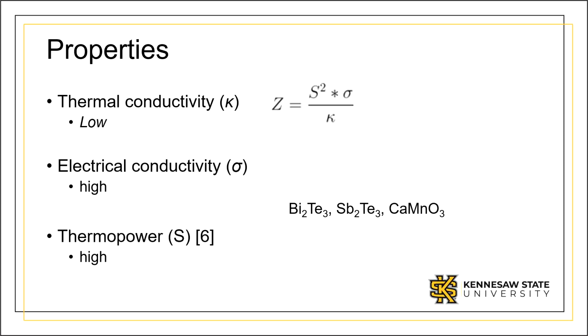There are three fundamentally important properties of a thermoelectric system that must be optimized in order to produce a near-ideal system. Unfortunately, these three properties are closely related and are usually inherent properties of a material. An ideal thermoelectric material will have a high electrical conductivity to minimize Joule heating, a high thermopower to maximize voltage generated per degree of temperature gradient, and a low thermal conductivity in order to maintain a high temperature gradient between the sides of different temperature.